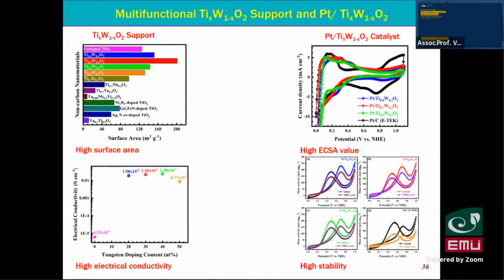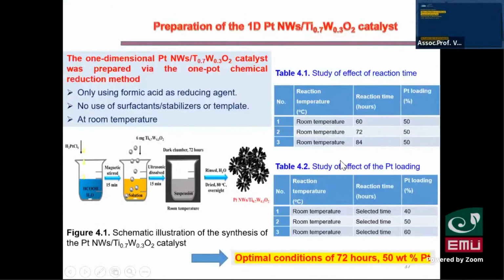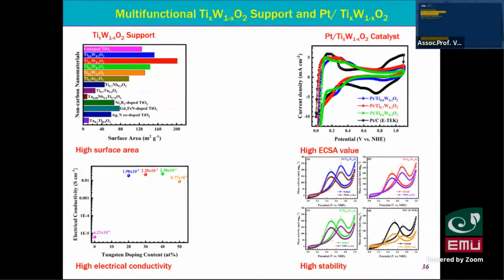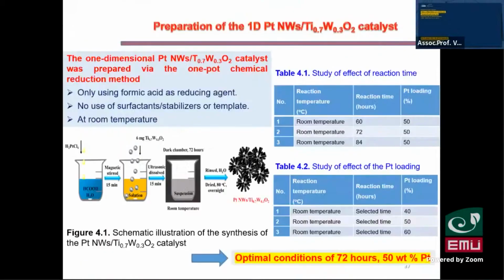We found that different ratios of tungsten with titanium oxide affect the properties differently - the surface area, the electrical conductivity, stability, and also some structural properties. We found that the optimal ratio is around tungsten 0.3 or 0.2.